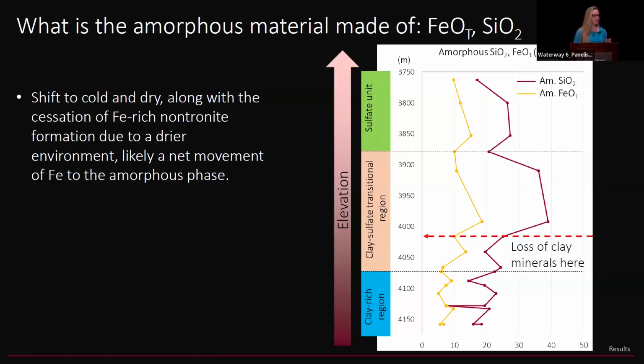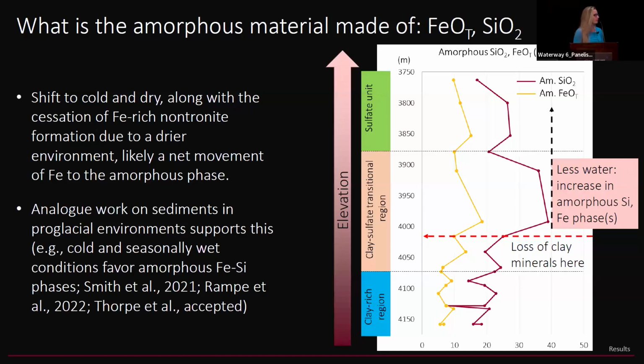If we're not forming our iron-rich smectites, and our smectites in Gale Crater are very, very iron-rich nontronites, I think a lot of that iron is getting pushed into the amorphous component. Also, my supervisor, Liz Rampey, has done a lot of analog work on sediments in proglacial environments and also finds a lot of iron silica rich amorphous phases. So this, I think, is a reflection of lower water rock ratio; generally drier, but not completely dry environments favor amorphous iron and silica phases. And whether these are one phase together or separate is something that we're working on.